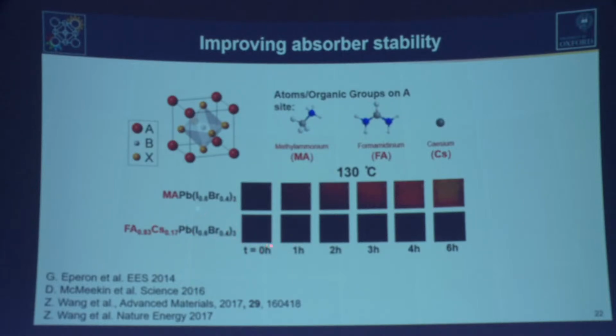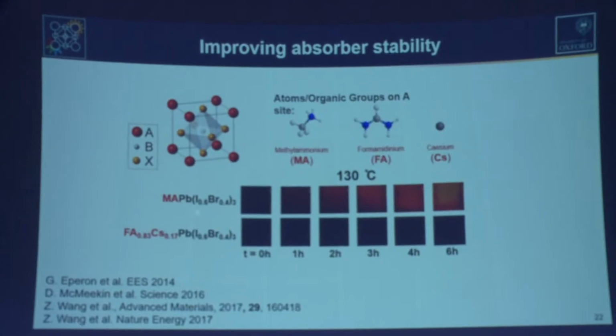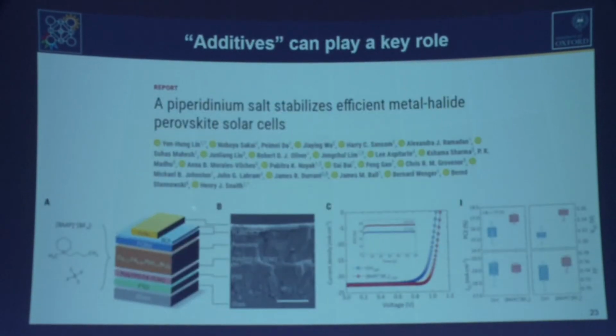To illustrate the improvement in stability, these films are held at 130 degrees in air, and over 6 hours these films don't discolor, whereas the ones including the more volatile methylammonium do. So that was an important step forward.